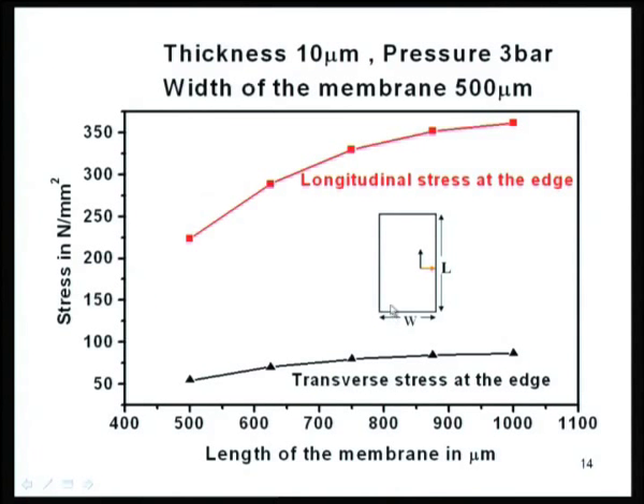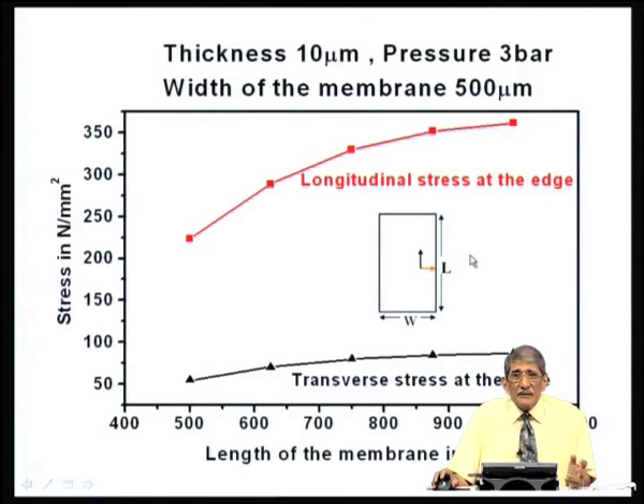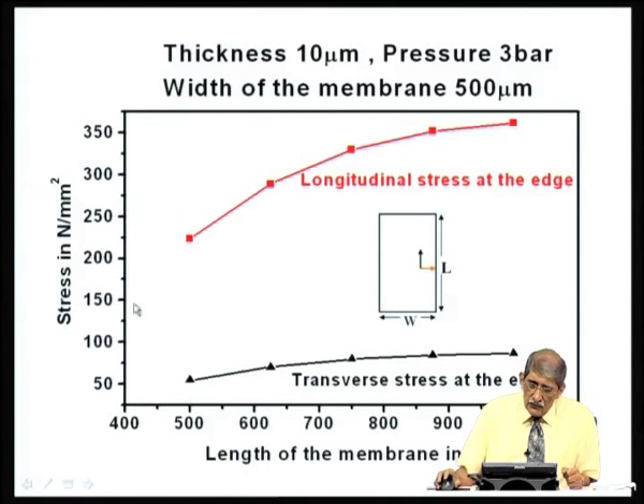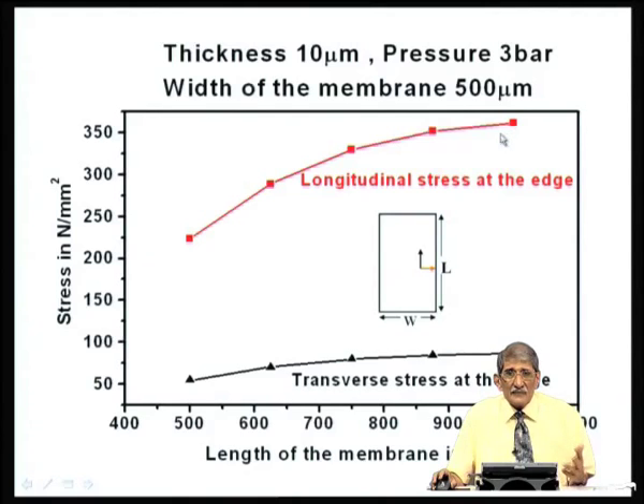Now, if I increase the length L and make it double, width 500 micron and length 1000 microns, the stress at this edge, the longitudinal stress, which was originally 225, becomes almost more than 350. So, this stress is more, that means the strain on the resistors will be more, that means for the given gauge factor delta R by R will be more, that is, sensitivity will be more. The transverse stress is not increasing much, so we are not going to use that. Since the length is increased, you will have more stress and the sensitivity will be better.